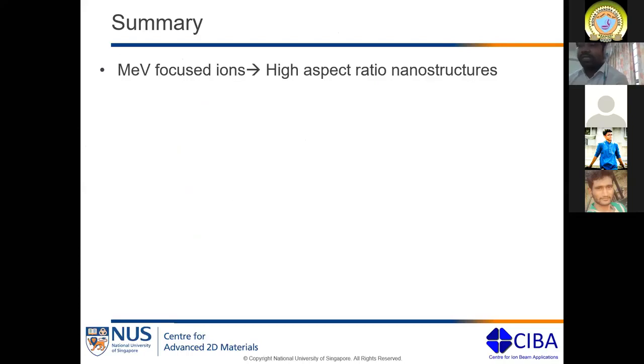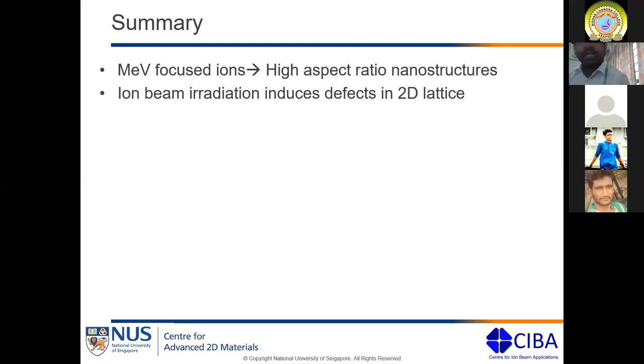So with this, I would summarize my talk. We can use MEV focused ion beam for high aspect ratio structures. We can use ion beam irradiation technique for creating defects in 2D lattice. And this kind of defects, or single vacancy or mono vacancy defects, can be used for water purification, because for water purification, the efficient defect range should be within 2 nanometer in size. So if you can tune the pore size within 2 nanometer, that would be great. That would be the holy grail of the whole research.